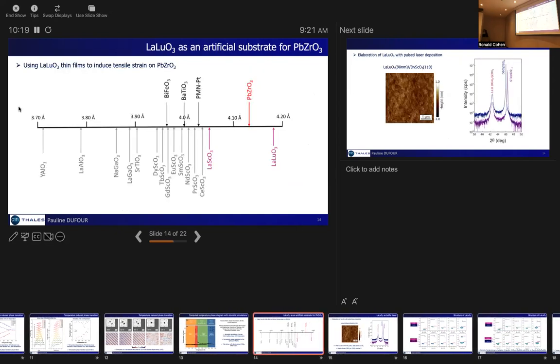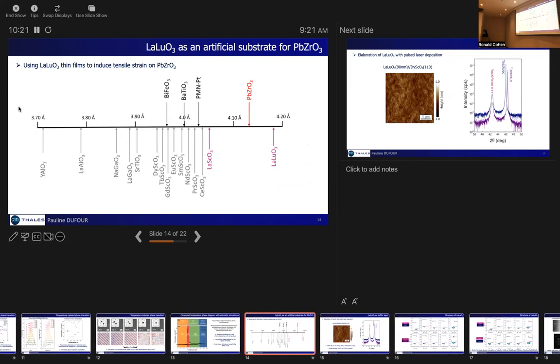So for the last part of my talk, I will show you how we tried to induce tensile strain in our thin films, as it was predicted to stabilize the antiferroelectric phase. So here I reported the lattice parameters of the standard perovskites. You can see that in gray are the usual commercially available perovskite substrates that induce a relaxation of the strain for PbZrO3, which is kind of in the no man's land of perovskites.